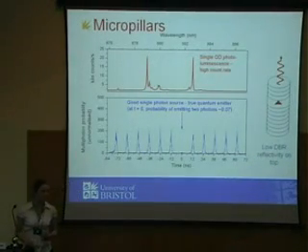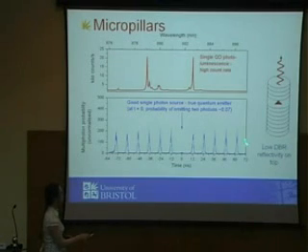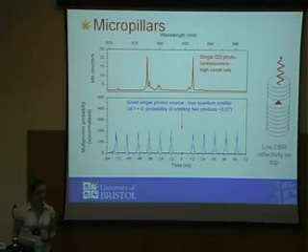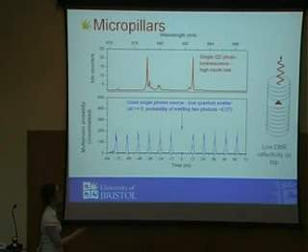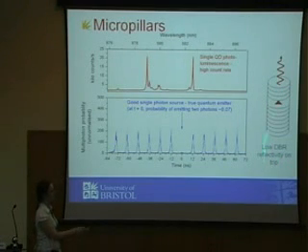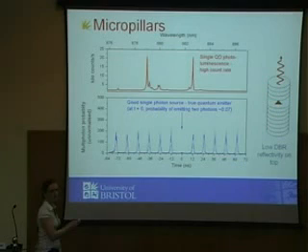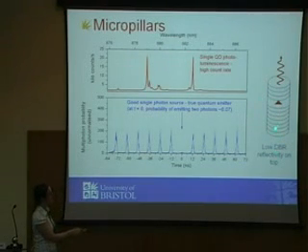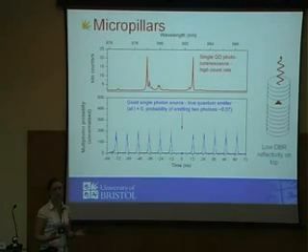We also use micropillars, and I'm showing you a good example of this. We use micropillars mainly as single photon emitters. By taking off a few of these mirrors at the top, all the light is channeled into the vertical direction. So we have the increased interaction, so it emits photons faster, and you can channel the light upwards, which makes it much easier to collect. In a normal semiconductor with quantum dots inside, most of the light is totally internally reflected, and it's very difficult to collect.